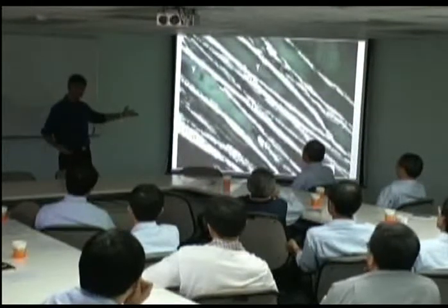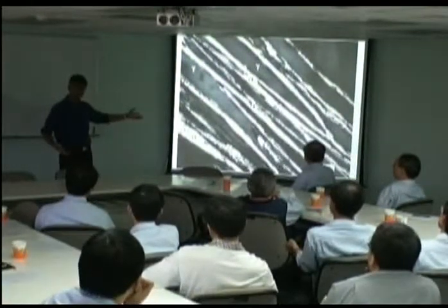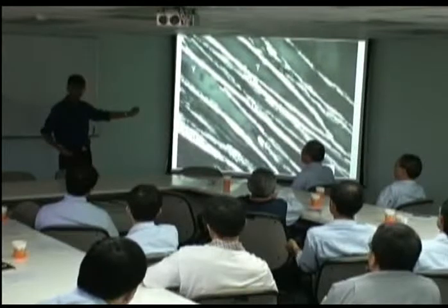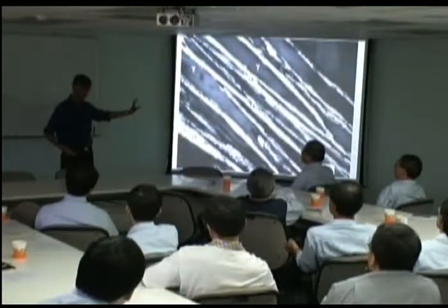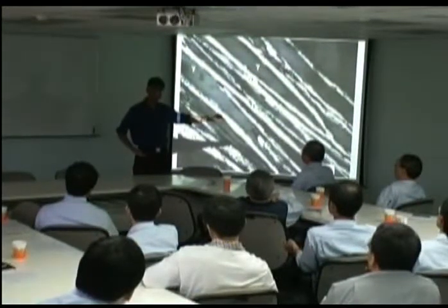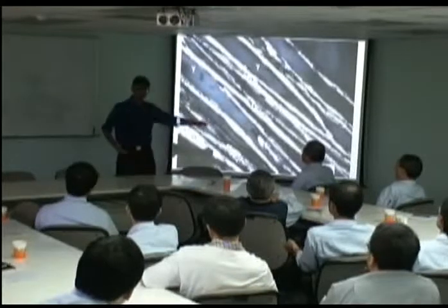We can produce a grain size of 20 nanometers. This is the hardest bainite ever produced. It's got a hardness of about 790 Vickers. And it has a toughness of about 40 megapascal root meters. And it's a dirty steel. We have inclusions about 2 micrometers in size. It took 10 days.